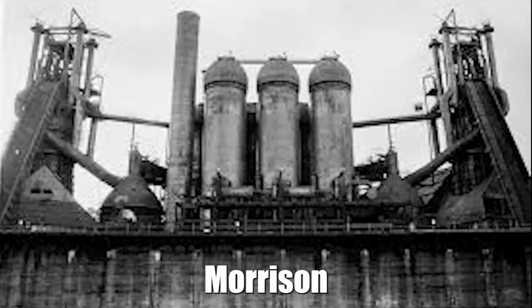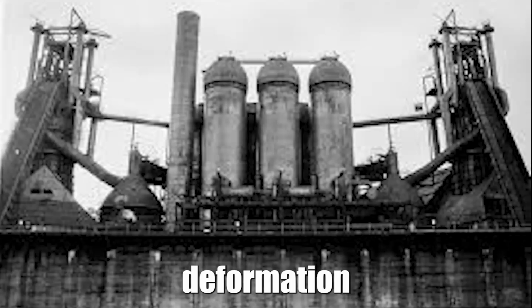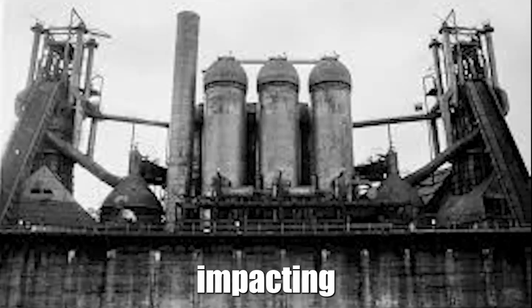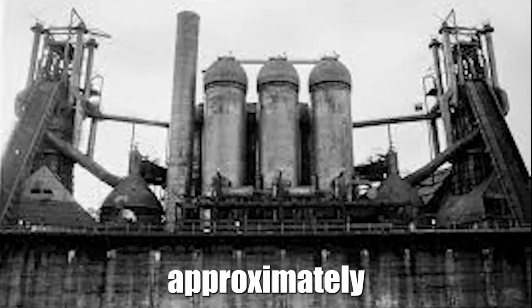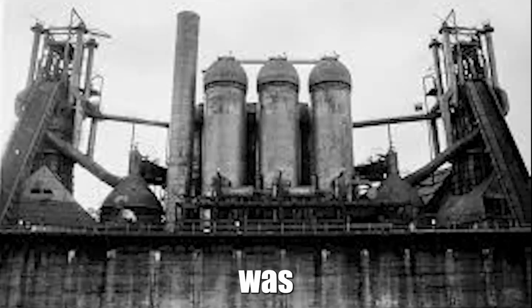Through binoculars, Morrison watched the impact point, looking for the telltale signs of penetration. Deformation of the backing plate, spalling on the interior surface, catastrophic fracture of the armor. None of those occurred. The round struck the plate exactly on the center line, impacting the experimental manganese-enriched surface layer. The projectile penetrated approximately 20 millimeters before its momentum was arrested by the tough, high manganese steel. The plate deformed but didn't fracture. No spalling occurred on the backing face. The armor had performed exactly as Morrison's metallurgical analysis predicted it would.